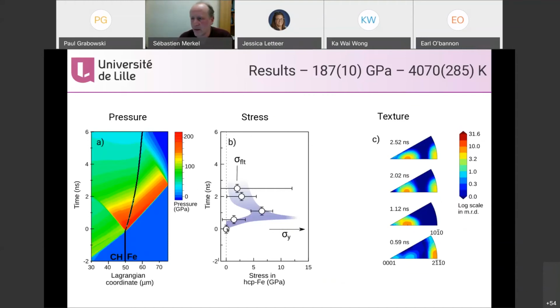And this is the X-ray diffraction measurement evaluation of stress and texture. So here we're plotting stress as a function of time. The dots are the points where we actually measured X-ray diffraction data, and the blue is just a guide. And then the texture that we measure in the sample. I will focus on the texture a little bit. So 0.59 nanoseconds after transformation, we get a texture with a maximum at 2 minus 10.